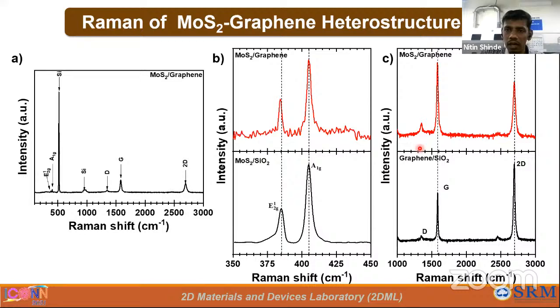Also we can see here the Raman spectra before and after deposition on the graphene. This is just the graphene transferred on Si substrate. We can see the G band and 2D band, and they are very nicely visible. But after deposition of MoS2 on graphene, these three bands simultaneously change in intensity, because of strain or some interlayer interaction. That's why the intensity of the E2g and A1g bands changes. Also, the defect band increases, because of heating or maybe strain.